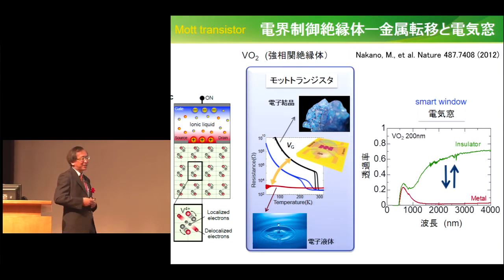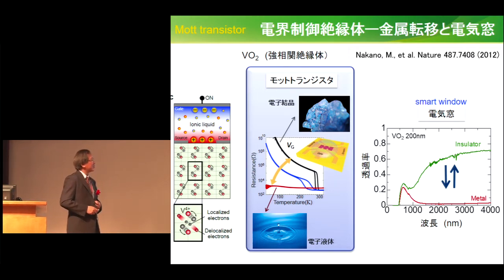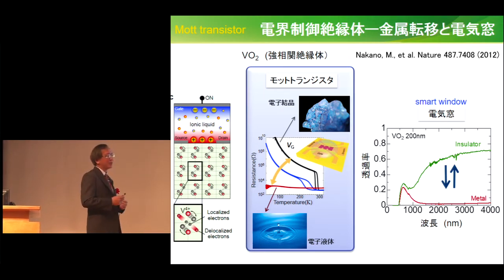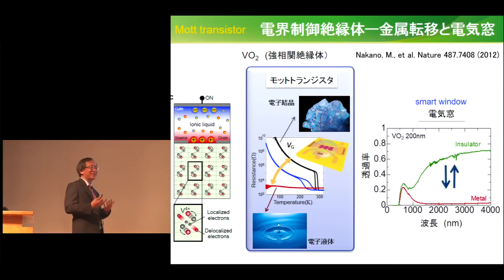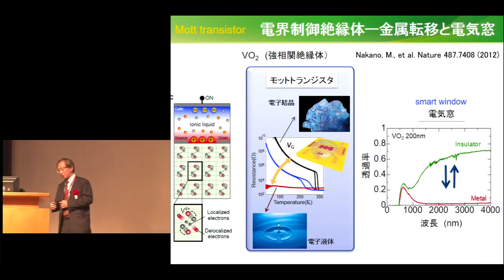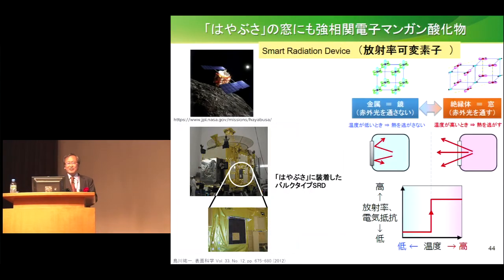By applying the electric field, there is a gate to make a transistor. And with a transistor, with 1 volt of voltage, at lower than room temperature, the insulator turns into the metal, and the metal state is maintained. Crystal turns into the electron liquid. And this change was brought about with the application of the electric field. If the electrons are moving a lot, it's like a mirror. If the electrons are immobilized, it's like a window. So in the near infrared, insulator and metal states are switched. So by using electric field, you can control the transmittance.